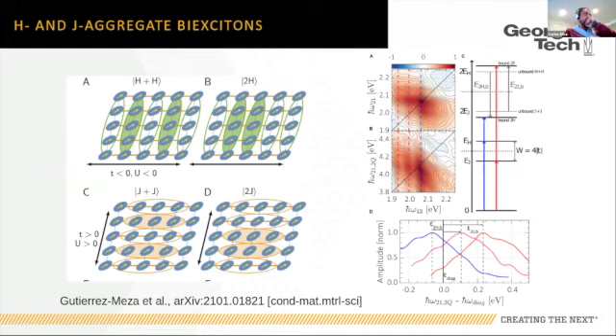So I'm almost out of time. I've almost talked for 20 minutes. Let me just point out that if I take a cut here in the 0, 0, what would be the 0, 0 of the linear spectrum for the H aggregate, this is a cut of the 0, 0 of the J aggregate in the linear spectrum. I can then see that there's a distribution, and then plot the amplitude of this cut versus the relative energy in this 2 quantum energy axis relative to the diagonal. So 0 is the position of the diagonal.